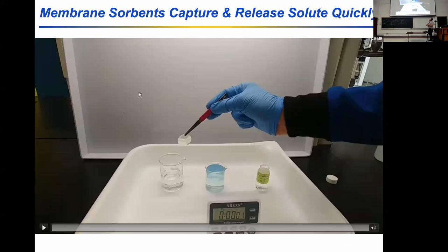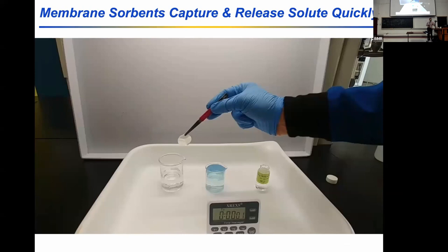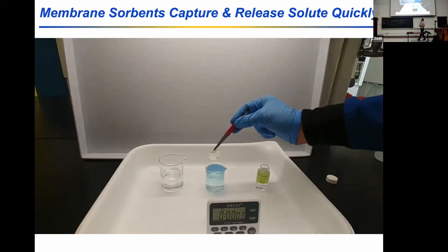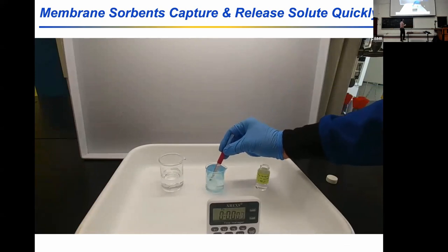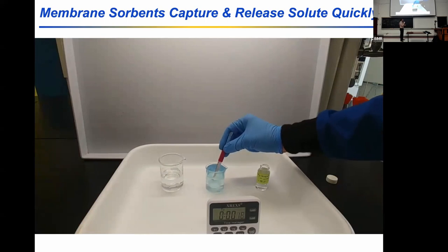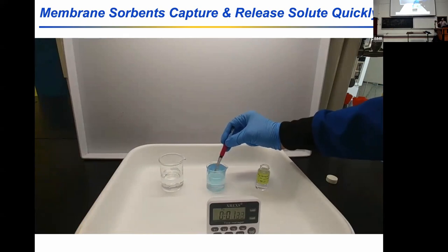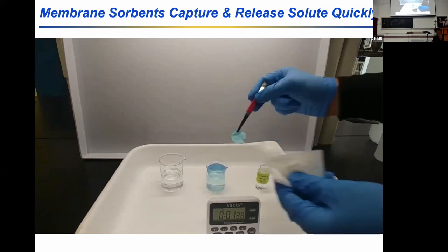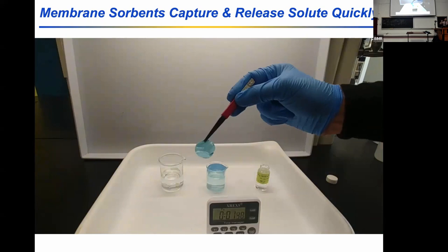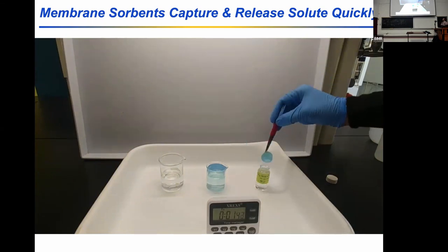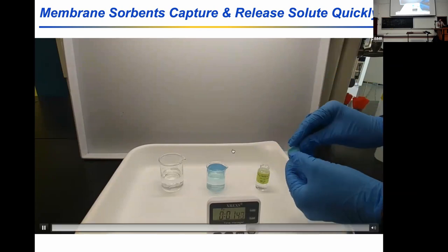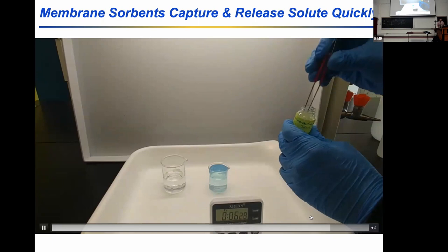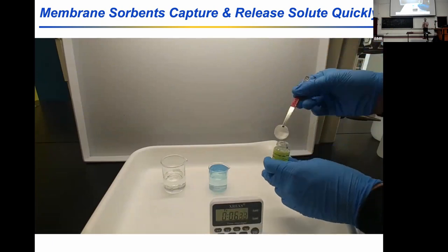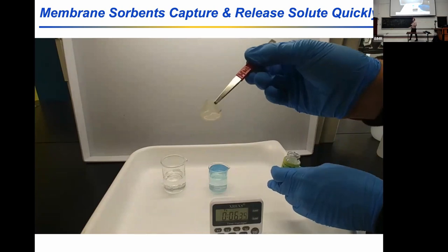This video shows the rapid mass transfer that results from membrane sorbents. We take our initially white opaque membrane, and then we're able to swish it around a little bit in our copper solution for 90 seconds. After 90 seconds, it comes out as this brilliant blue color because of the high concentration of copper ions that have been fixed to the surface. Then we can put it in a release solution, shake it around a little bit, and pull it out, and it's returned to its original opaque white color because the copper ions have been released.